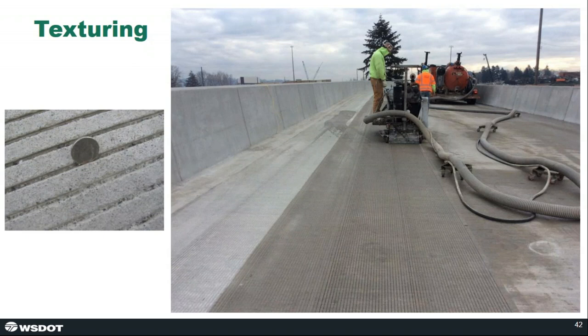Also, there's some concern that by texturing the concrete while it's still plastic, and this texturing I'm talking about is usually accommodated by just dragging a rake across the concrete surface, we're effectively increasing the surface area of the concrete, which actually speeds up evaporation from the surface, which is not at all desirable from a curing standpoint. So we've seen good results with this longitudinal diamond grinding requirement for a bridge deck texture.